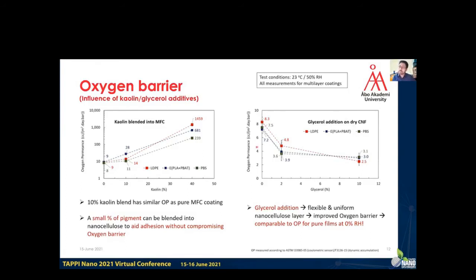And on the right, we have the influence of plasticizers such as glycerol on oxygen barrier. We see that as we add glycerol to nanocellulose, the oxygen permeance goes down. It could be that the glycerol addition makes a flexible and uniform nanocellulose layer and therefore has a better oxygen barrier. And actually, it is comparable to pure films at 0% humidity.